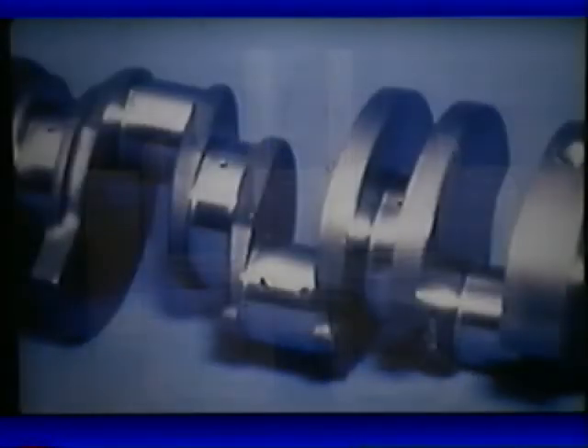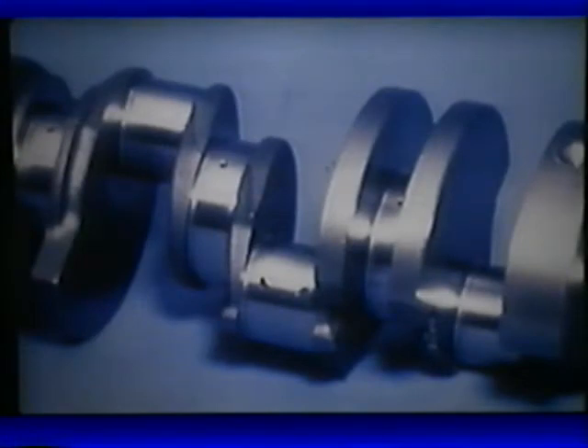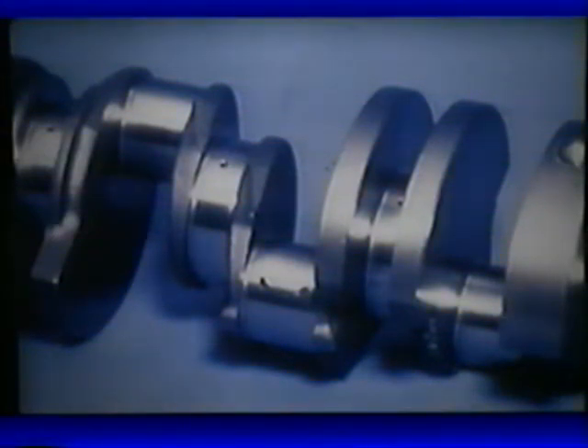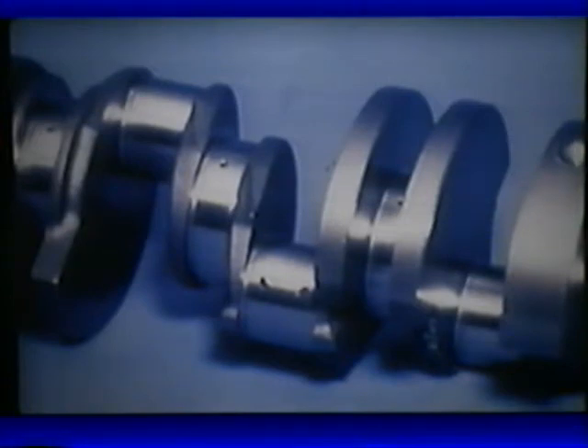Finally, journal dimensions are closely controlled in the range of plus or minus 8/10,000ths of an inch, and bearing surfaces polished to a surface finish of 10 millionths. All of this is necessary to produce a crankshaft which will perform well over a long service life. Increased friction and increased bearing wear, or even seizure, could occur if the surfaces were not polished this finely. Significant problems or reduced bearing life could result from a journal surface polished above 10 millionths of an inch.